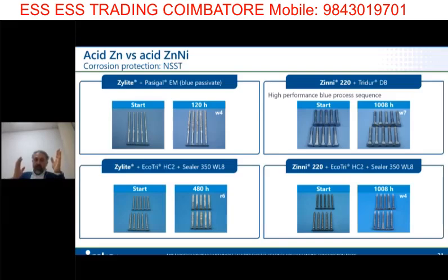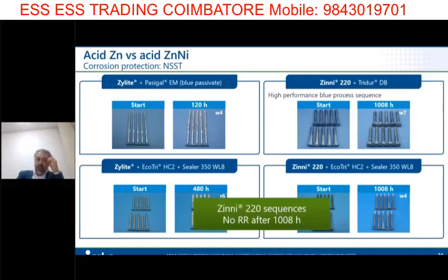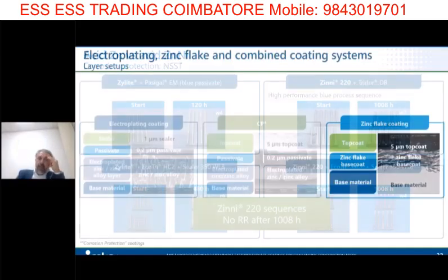In this case, we are talking about EcoTri HC2 as our passivation, in combination with the Sealer 350 WL8 that we already presented some slides ago. Here, the jump is even bigger, because at 480 hours, only with the zinc, we can see the presence of red rust in some cases, while on the zinc nickel part, we don't have any red rust, but just some white rust presence at 1008 hours. So you can easily see that the jump in this case is coming from the zinc nickel deposit.